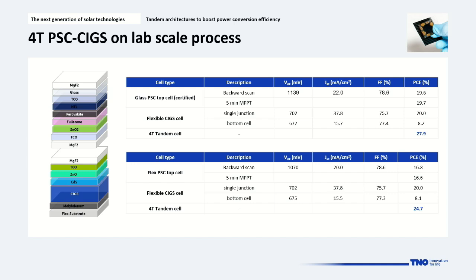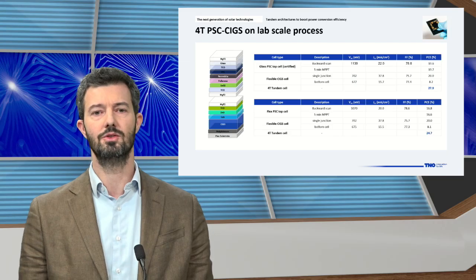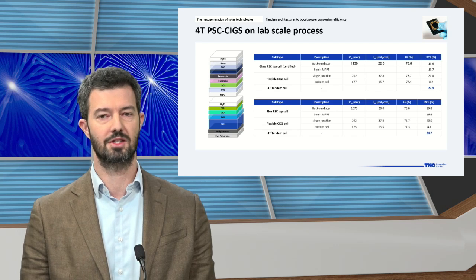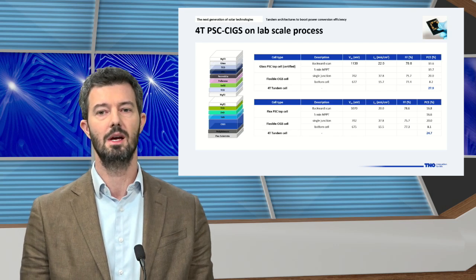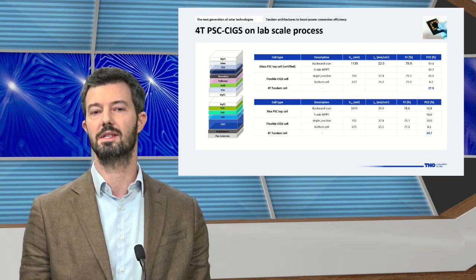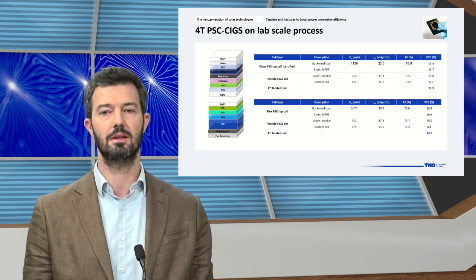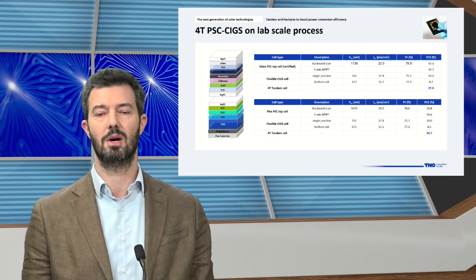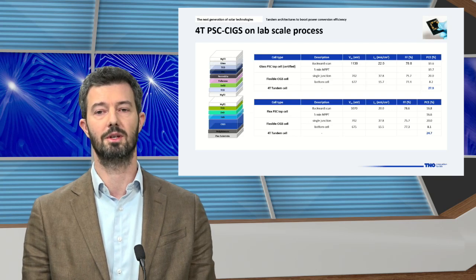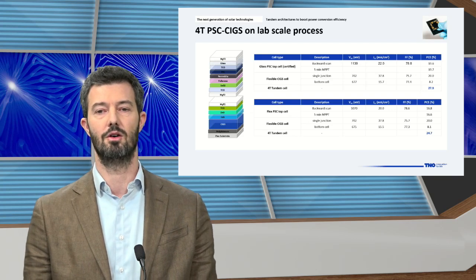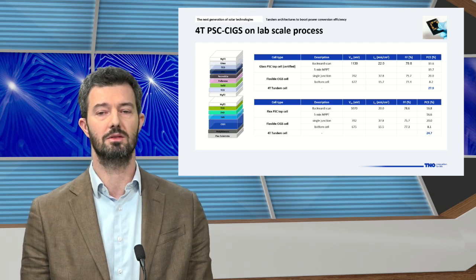And because we use a flexible CIGS, we also tried to combine it with a flexible perovskite top cell, the one that Jude mentioned before. This device was not the last generation, so it's not perfectly optimized, but still, when combined with the same flexible CIGS with 20%, it can provide a 4-terminal power conversion efficiency of almost 25%. So again, we get a gain of 5% with respect to using just a single junction device.